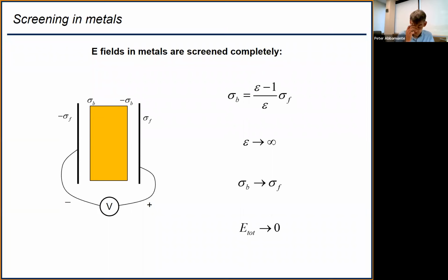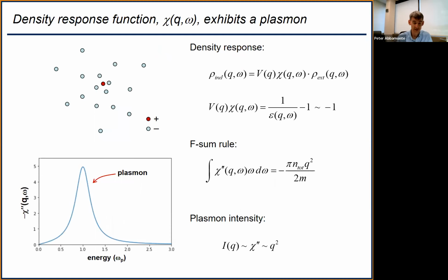Okay, so what does this have to do with collective excitations? If you have a system that screens, it implies the existence of a collective mode. So another way to view the screening of a system is in terms of its density response, which is usually written chi of Q and omega. So this quantity describes how a system responds when you put some external charge in it. So suppose